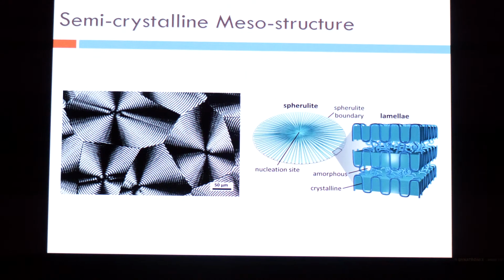Because in between the two lamellae, you have a mass of polymer chains which are entangled and which are amorphous. They don't have order in them. So polymers are typically never 100% crystalline. They are always semi-crystalline. Typically about 40%, 50% is crystalline. The remaining 40-50% is amorphous.